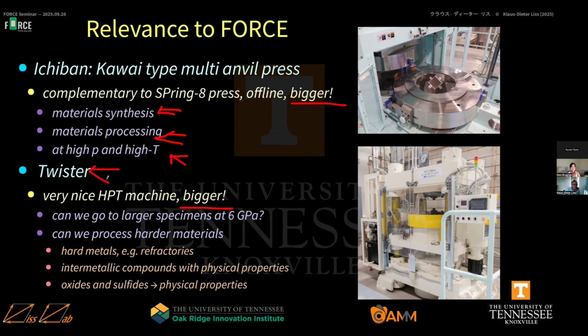The twister, I would love to use it a lot, and probably many people, because it's also from the dimension and the parameters bigger. So can we go to larger specimens at 6 GPa? We're processing at 6 GPa typically. Or what I wish is to process harder materials, that means harder anvils. Can we design, or have you designed harder anvils, e.g. for hard metals, like refractory metals, intermetallic compounds with physical properties. If you take Heusler alloys, they're very, very brittle and hard.